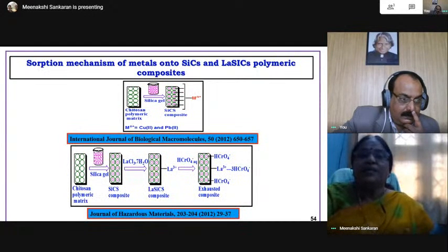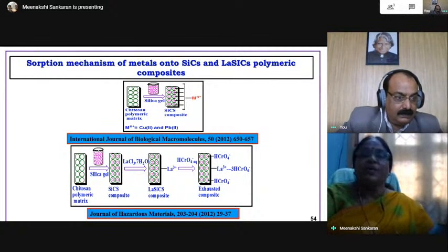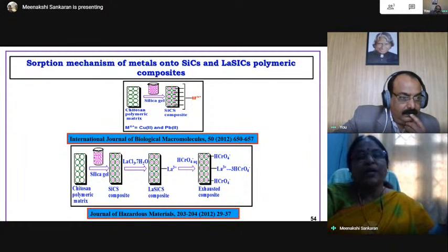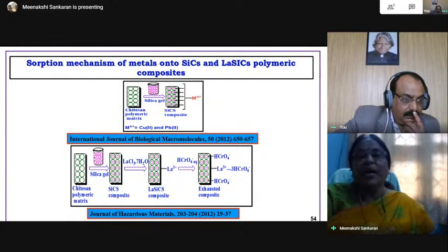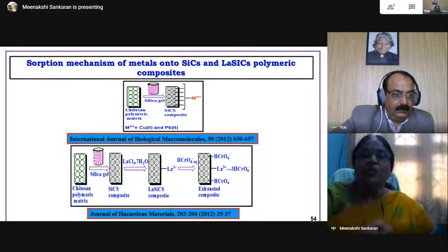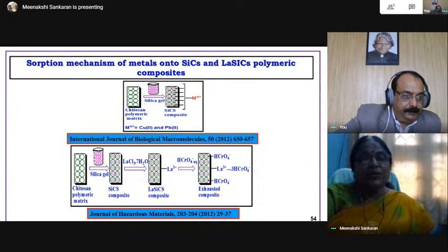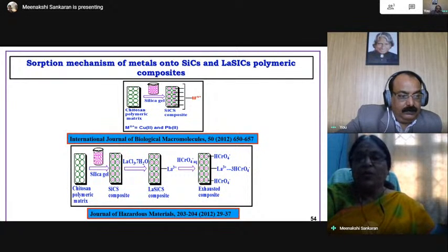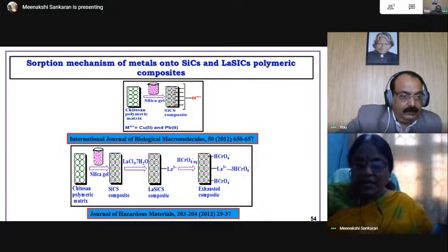So we have also used SiC, that is lanthanum loaded silicon chitosan beads, and silicon chitosan beads. When silica is introduced into chitosan, we can get composites. And another thing is the silica, when we make it as a composite, it can later be removed. It will produce small pores in the material, so that the pores can absorb metal ions. So we have made lanthanum chitosan silica composites and silica chitosan composites, which were able to remove fluoride by means of electrostatic interaction.